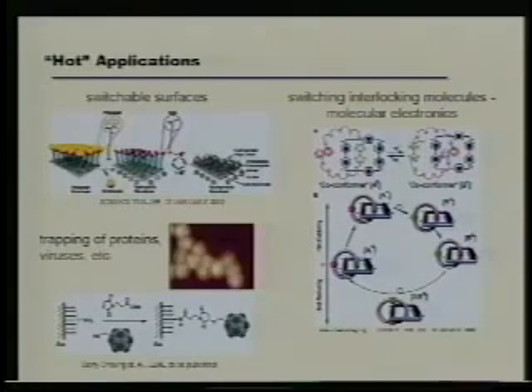And the third example that I'm showing here over on the right is these interlocking molecules. These molecules are called catenanes. And to first approximation, these are two rings that are free to rotate with one another. So they're completely separate. But these rings, you can actually get them to lock into conformation sites so they can switch. So these are molecular switches. There's been work, our group has done some work on actually using thiol chemistry to bond these things to surfaces. But you'd actually like to know what the conformation of these rings are with respect to one another.